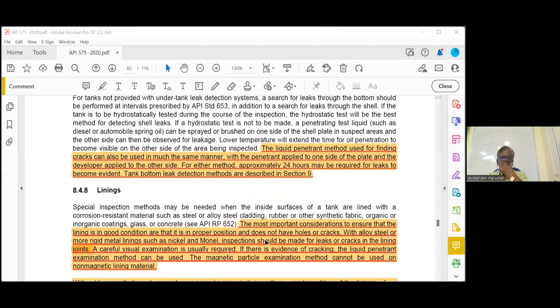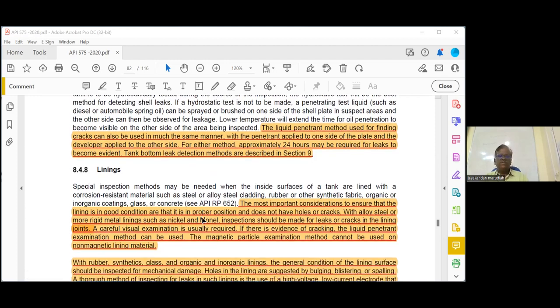Linings, 8.4.8, third line. The most important concern is to ensure that the lining is in good condition, in proper position, and does not have holes or cracks. With alloy steel or more rigid metal linings such as nickel and monel, inspection should be made for leaks or cracks in the lining joints. A careful visual examination is usually required. If there is evidence of cracking, the liquid penetrant examination method can be used. The magnetic particle examination method cannot be used on non-magnetic materials.